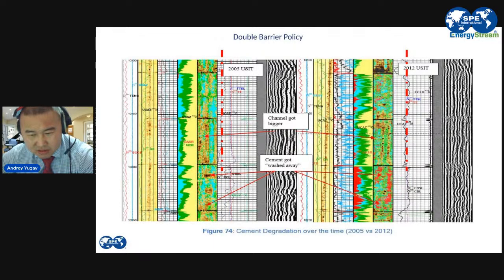Amplitude is this red dotted line. And then after some period, in 2012, we had a workover, and we repeated the same tool from the same service company. You can recognize it. We repeated in the same well and same interval. You can see there is a significant degradation of the cement, and the amplitude got shifted to the right side. So it's almost a free pipe now, and we see when there is gas coming from the bottom.